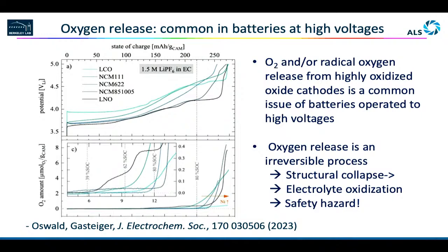However, you can see over here already the lithium cobalt oxide is doing really well. And sometimes we were amazed. Lithium cobalt oxide is the very first commercialized battery positive electrode 30 years ago. And it remains the highest energy density up to this moment. After 30 years of effort, it still has the highest energy density.